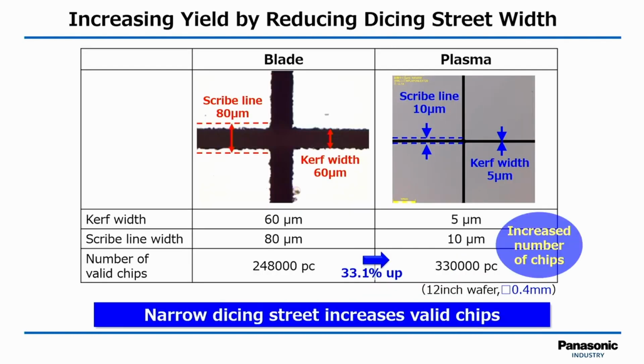You can see here an example of how yield can be increased. Kerf width has been reduced to 5 micrometers with plasma dicing. So if we take an example of a 12-inch wafer with a 0.4 millimeter by 0.4 millimeter device, and we reduce from 60 micrometers to 5 micrometers, you can increase the yield by 33%. So you can imagine the gains in production that can be achieved just by this process, which definitely plays a big role in the return on investment calculation.